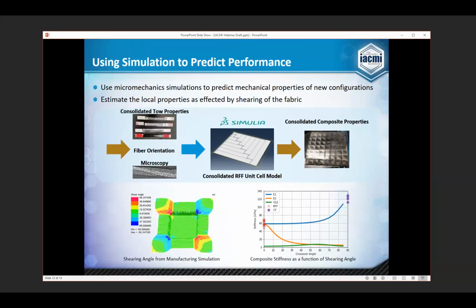But here I'm showing from our prediction model, comparing that to experiments that were done on the RFF cases for the stiffness. We're showing that, if we have a 0-degree crossover, so a 0 crossover angle means that we're at a 0-90 configuration. And then a 90-degree crossover angle basically puts everything aligned. And we're showing that at those limit cases, we're matching up really well with the experimental work that we had done to show that we're validating this model. And then it also shows, to Bob's point, that we're getting very good wet out as we go through the compression process because, as he pointed out, there's not a lot of distance that you have to travel to get the resin to fully impregnate inside the coated toe. So we're showing good results from that as well.